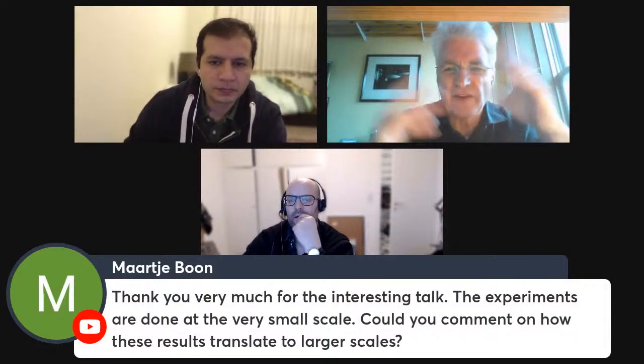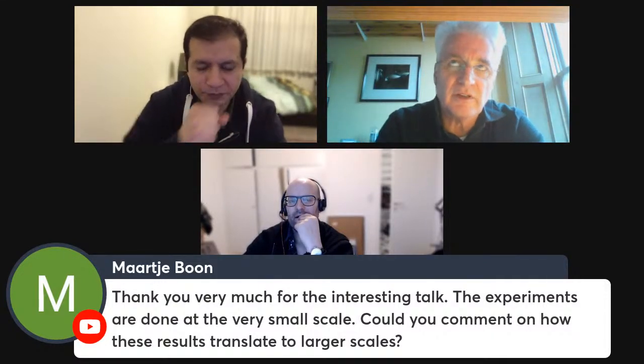So the intact samples with low heterogeneity are much more brittle, in a sense, than once you've got damage in the material or porosity. Then it's a kind of smoother evolution towards failure. It's less affected by jumps because you're blunted. A crack can only grow if there's another crack present. It's going to be blunt. The growth of the first crack is going to be blunted by one that it encounters, or if it grows into a pore or something like that. So the heterogeneity definitely helps to keep the system more stable, as well as affecting the other mechanical properties. But that's the main difference that you can back out from what I showed today.